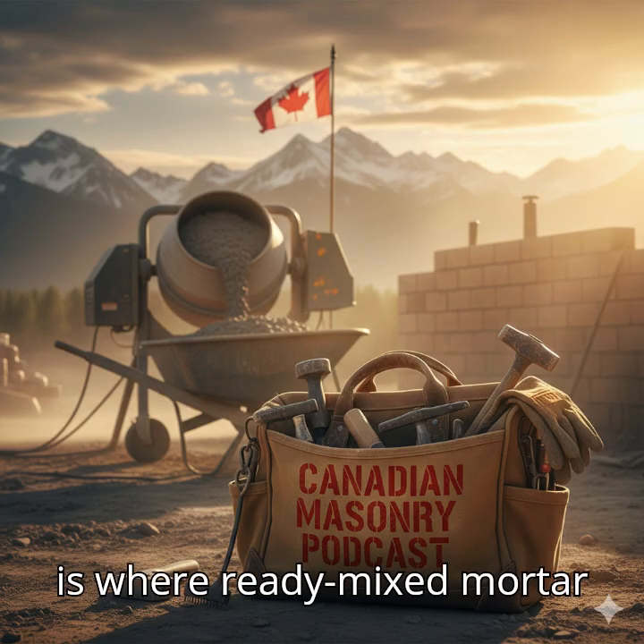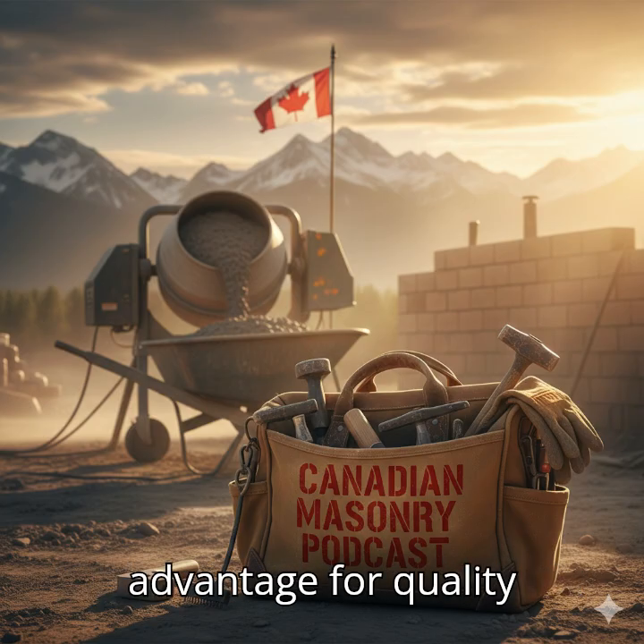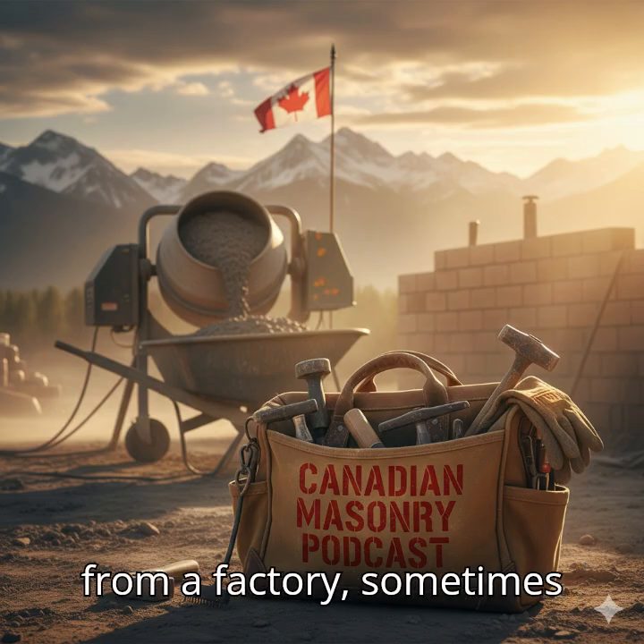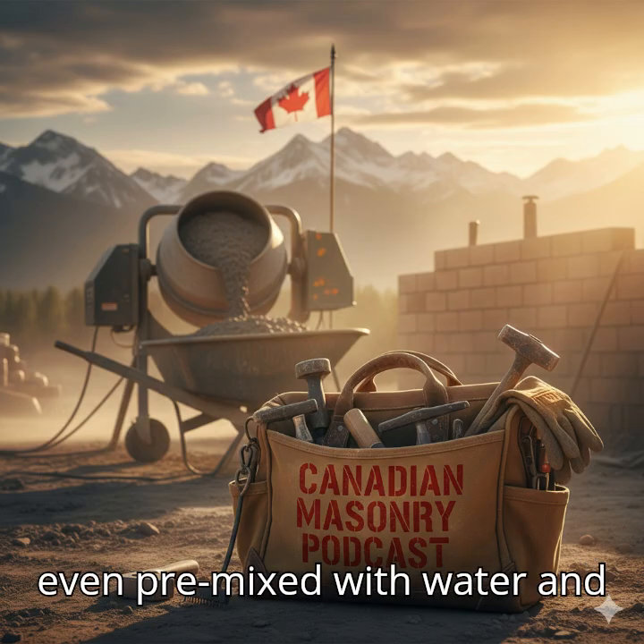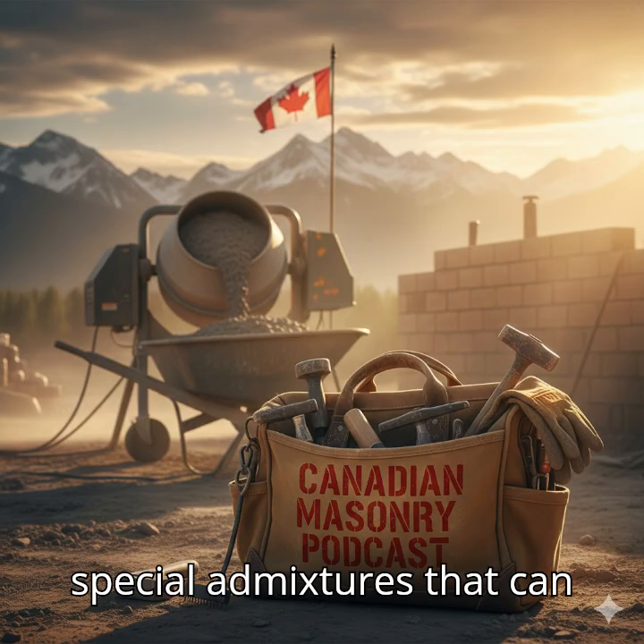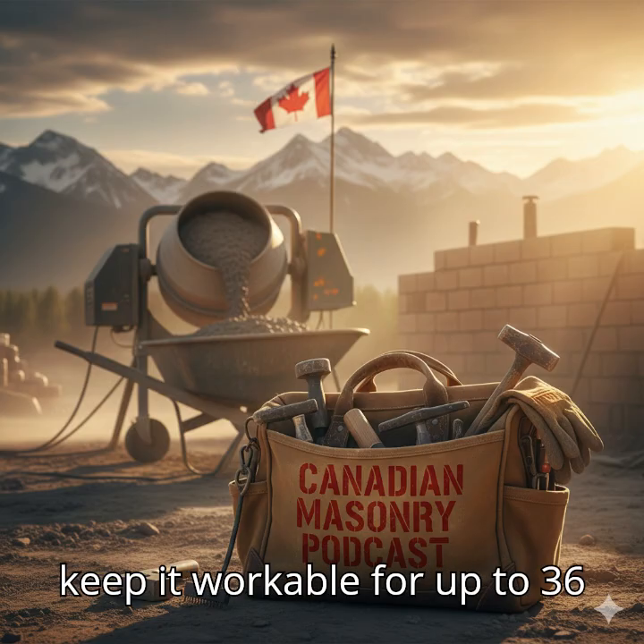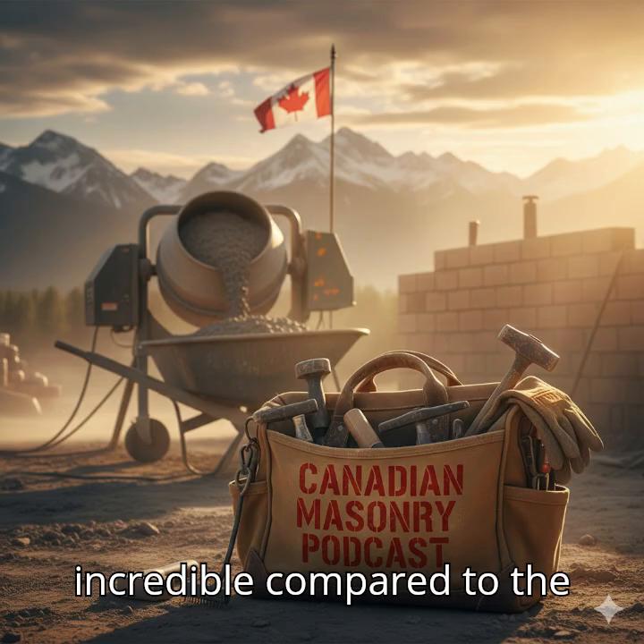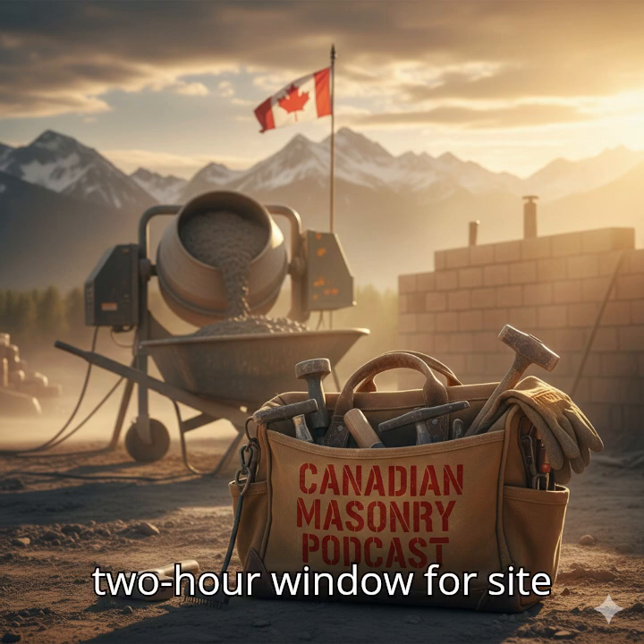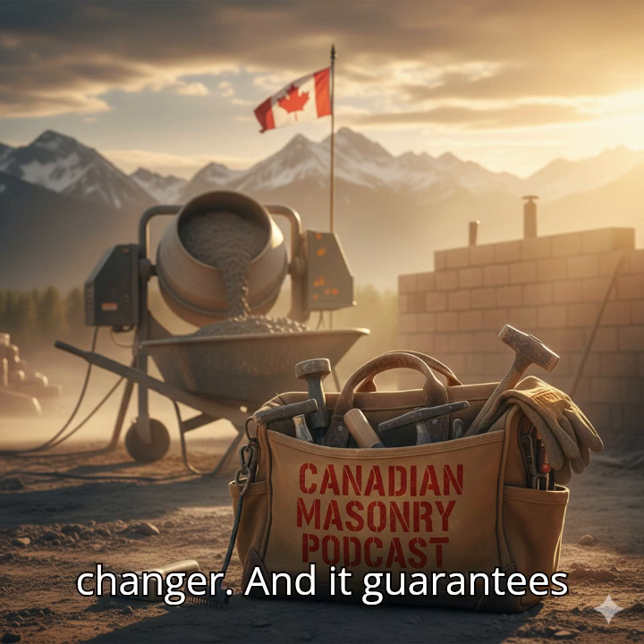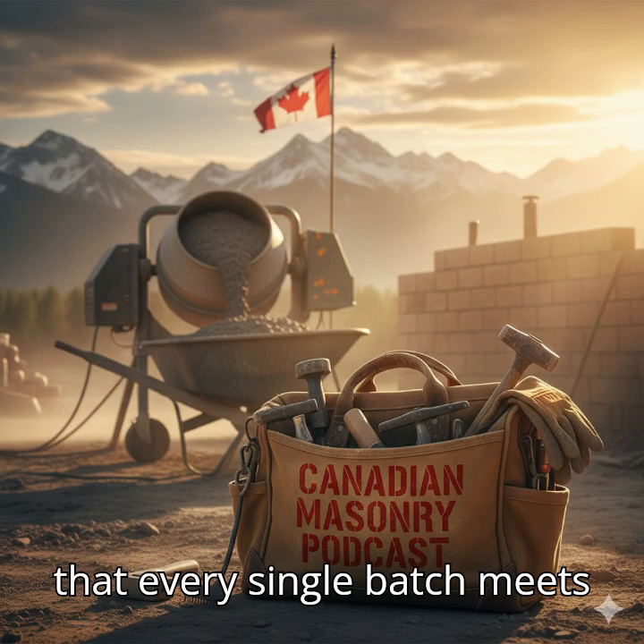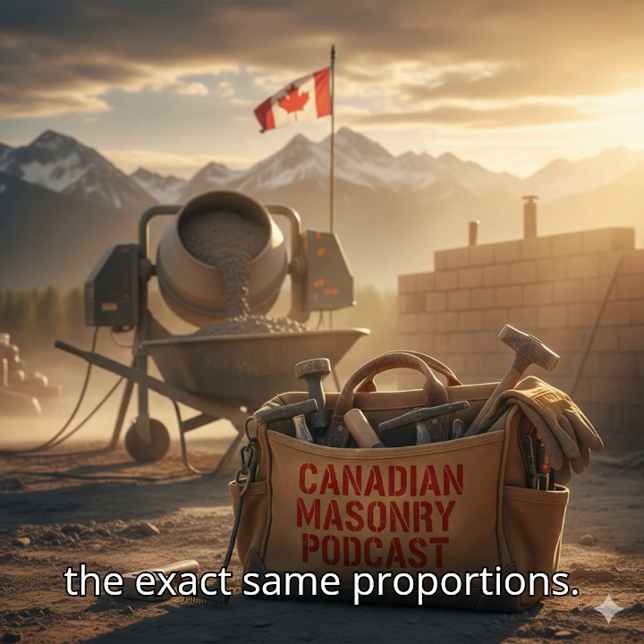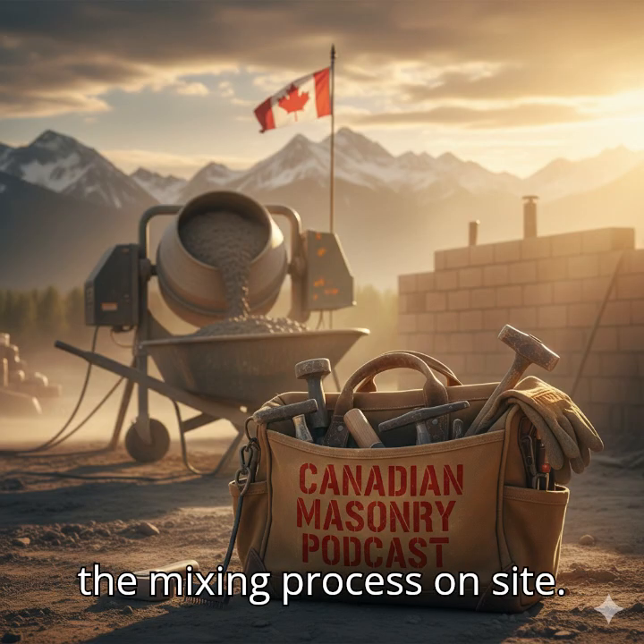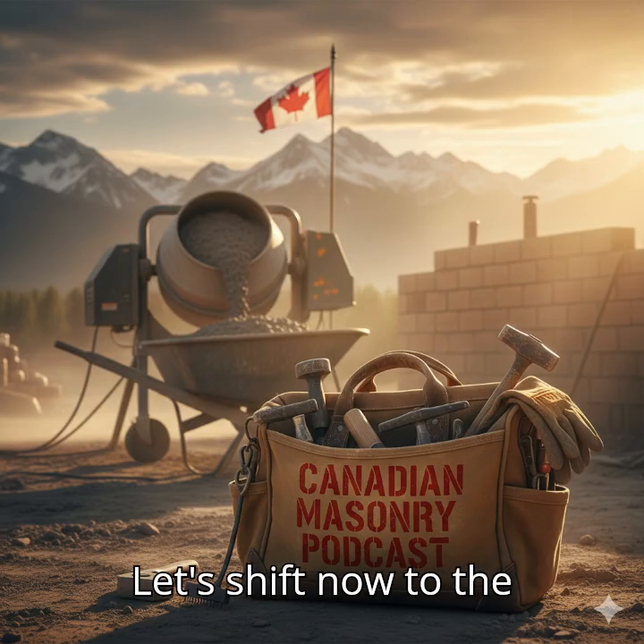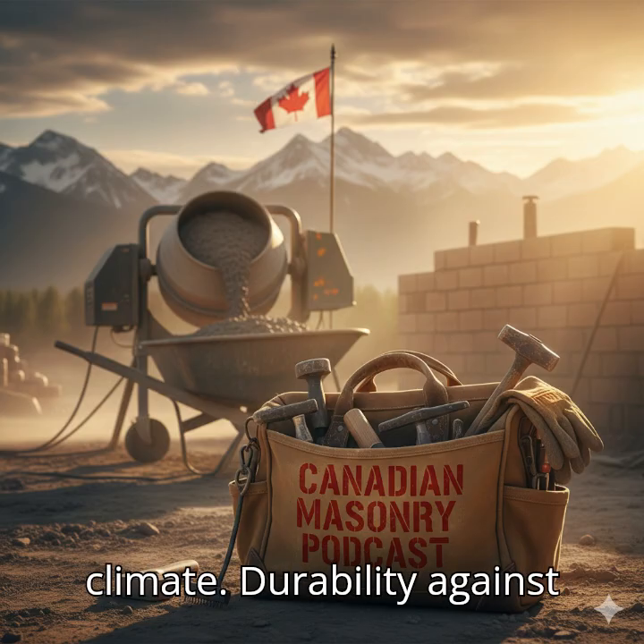Which is where ready-mix mortar comes in. It's a huge advantage for quality control. It comes pre-blended from a factory, sometimes even pre-mixed with water and special admixtures that can keep it workable for up to 36 hours. 36 hours? That's incredible compared to the 2-hour window for site mixed mortar. It's a game changer, and it guarantees that every single batch meets the exact same proportions. It takes human error out of the mixing process on site. Let's shift now to the biggest challenge, our climate.